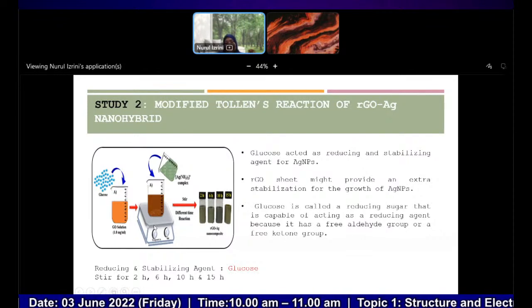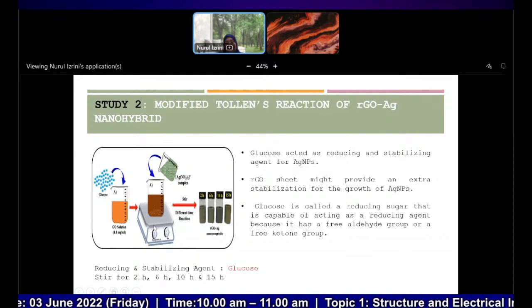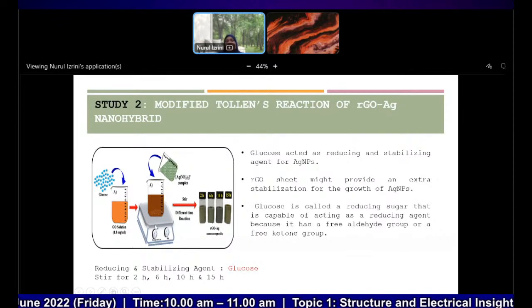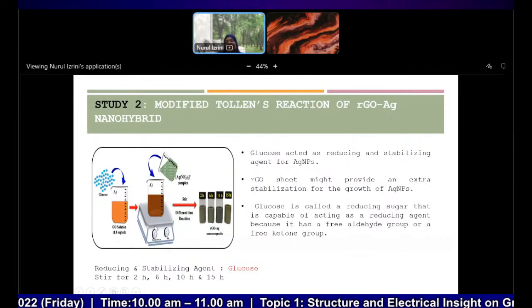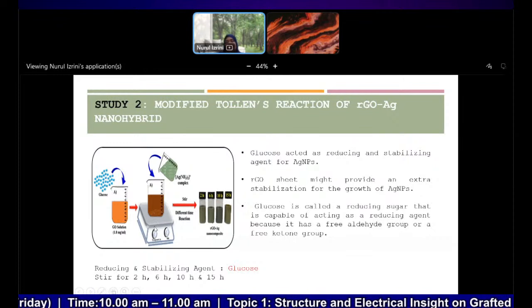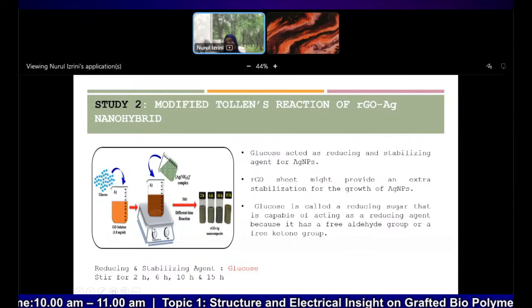Then the reaction is under stirring for different reaction times. I used 2 hours, 6 hours, 10, and also 15 hours, to see which reaction time produces good nanoparticles.